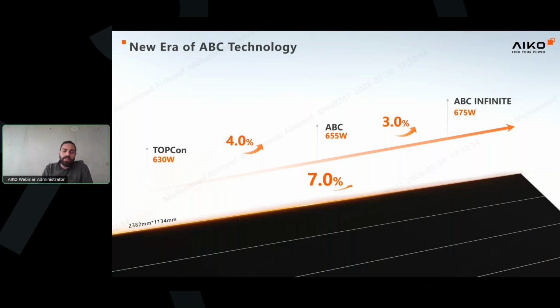So in the previous panel, we could provide 655 watt, and now by applying the infinite technology, we could also increase 20 watt more. And this also gives us the chance to widen and increase the gap between the AIKO back contact panels and our competitors from TOPCon with 30 to 40 watt. So it's 7% more power. And as you know, this is a big advantage in terms of yield or in terms of saving of the balance of system in case you just keep the same DC capacity. So let's move on and see what other technologies and how we could achieve this development.